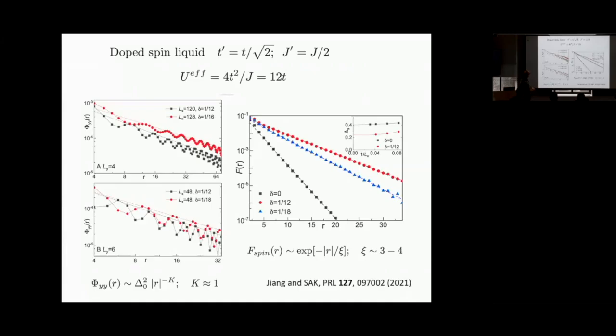And this is a log-log plot. So what you're supposed to see is that these superconducting correlations fall with a power law. The power law is close to 1. So that corresponds to a strongly diverging superconducting susceptibility.